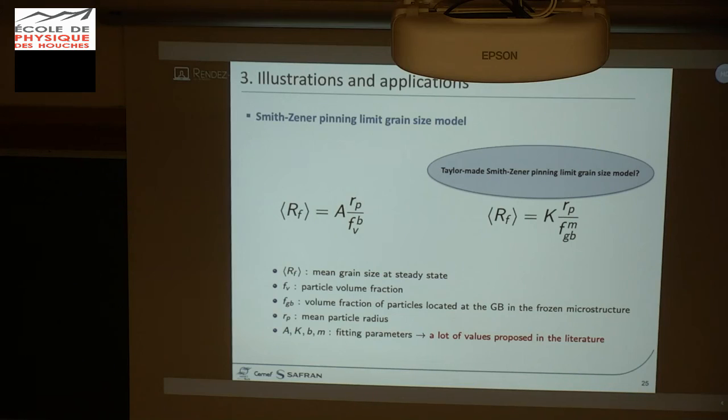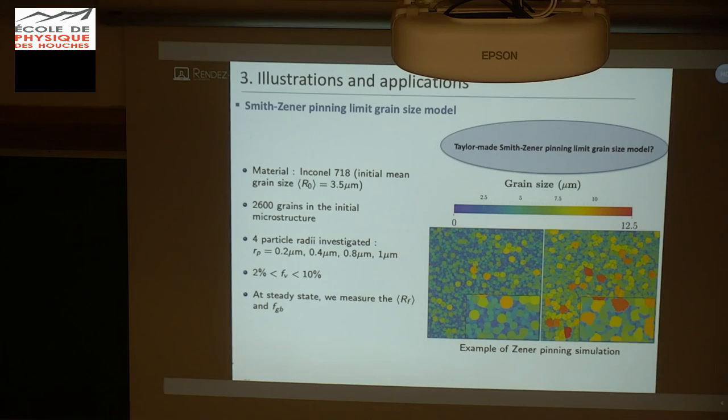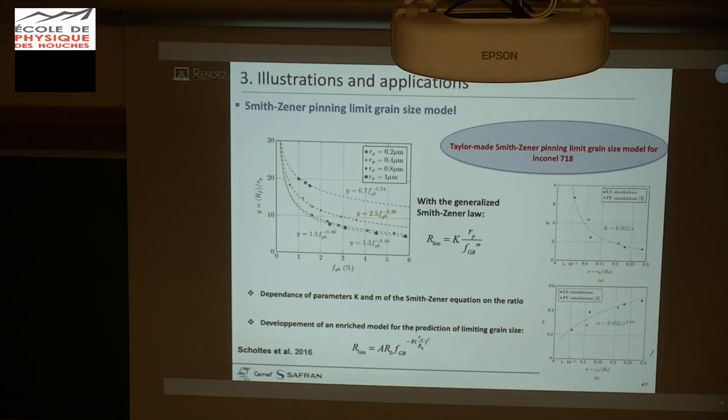And you can see in this equation the definition of the mean grain size, with r as the mean radius of second phase particles, and F the volume fraction of the second phase particles. It's well known that we can relate the mean grain size of the polycrystal to the definition of the second phase particle population. And in fact, you can improve this equation by some numerical tests, using a large scale of second phase particle populations numerically with different density. You can finally build a numerical test plan and, by homogenization, propose a new, optimized mean field equation to predict limiting grain size for nickel base superalloys. Okay, so I'm going to stop here.